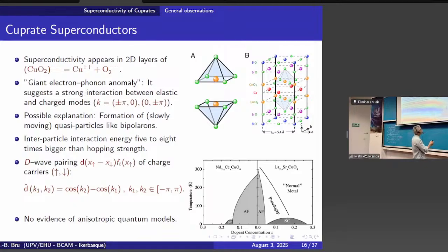So what happens if you start to dope it? For example, this compound adds some holes. If you have a Mott insulator, you have basically an integer number of fermions in each lattice site, and you break this. So what's going on is when you dope it, the antiferromagnetic critical temperature rapidly decreases, and then you have the appearance of a superconducting phase, depending on the doping, with the optimal doping giving the highest superconductivity. And then there is another critical temperature, which is a pseudogap regime that I will come back to. So it's like a semiconductor. You dope it, and by doping it, you change drastically the behavior of your compound.